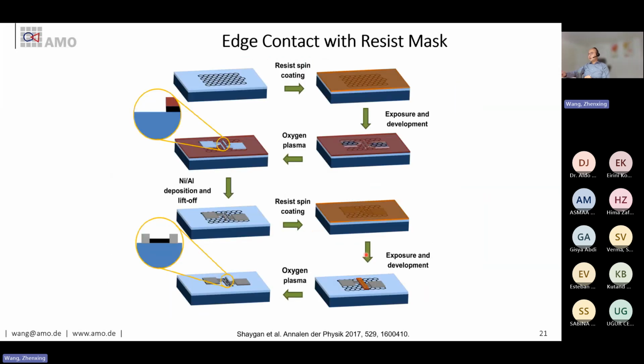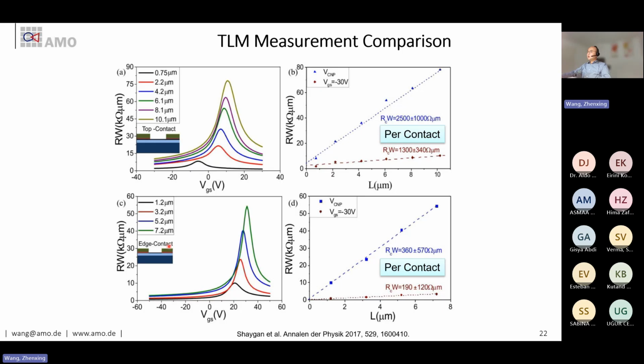So what we proposed many years ago is to simplify this procedure. So this is our paper, where we first transfer the graphene onto the substrate, and then we coat the graphene, and then we expose the area where we want to deposit the electrode, and then we etch the graphene in this window. So then you achieve a cross section like this, and then you deposit metal directly here. Then you achieve actually an edge contact directly. Afterwards, you do another spin coating, and then protect the channel, and then pattern the channel. So in the end, you get something like that. So this is a very easy approach to achieve edge contact. And you can see that we also achieve like 360 ohm micrometer or 190 ohm micrometer contact resistance.